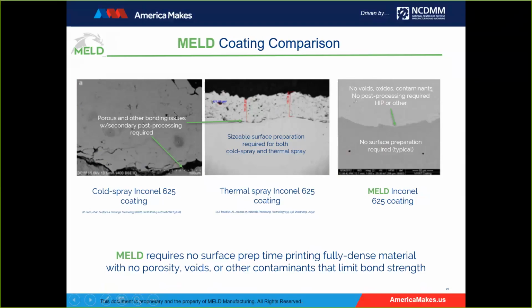And depending on the surface area of the application, a reasonably long time to prepare that surface before the coating. By comparison, we do no surface prep. We immediately meld the material onto the application. We get a fully dense bonding because at that interface, we plasticize both materials. In this case, this is the Inconel and this is a HY80 steel. So we're joining dissimilar metals and we're plasticizing them both at the interface, creating a strong metallurgical bond. And now I'm going to walk through that application to point out all the capabilities of MELD.